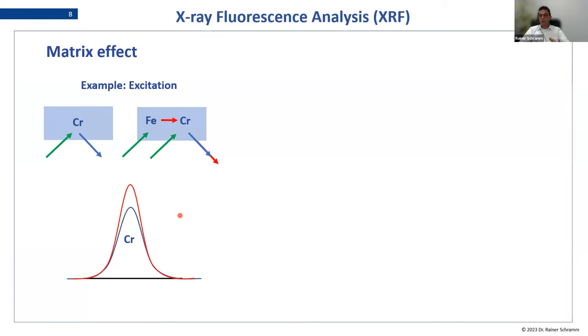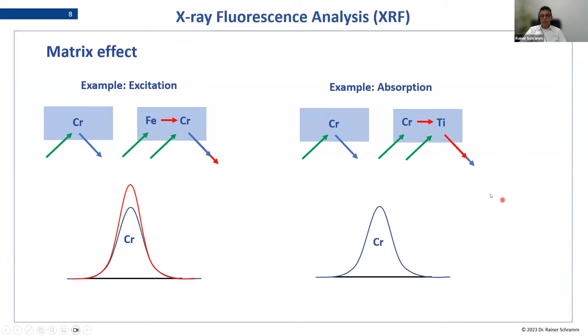Yeah? So here we have a kind of a secondary excitation, which will increase our signal without changing the concentration of chromium in the sample. The same would be opposite if we have an absorption, that means that beside chromium, our element, we have an element like titanium, lower atomic number than chromium, and so low that titanium is able to absorb chromium fluorescence radiation. And this means that a part of the chromium radiation is used to excite titanium, and this results in a lower chromium peak. So here you see already the two important effects. In one case, our chromium signal is higher than expected, and in the other case, it's lower than expected. And this we call matrix effect.